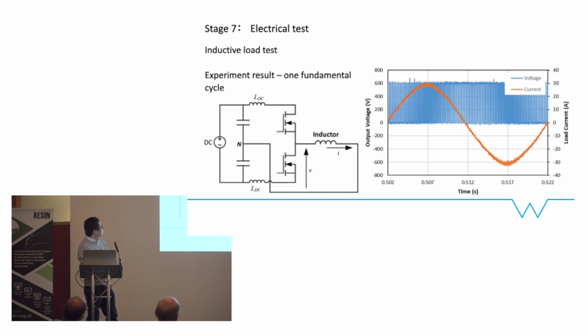All right, lastly, we did this inductive load test, in which we put our power module in constant switching operation. This is the diagram of the test circuit. With this circuit, with limited active power input, we can have large AC current circulating in this loop. This is one of the results at 600 volts DC link, and the current is 30 amps peak. We carried out different tests for switching frequency from 5 kilohertz to 20 kilohertz, and current from 10 amps to 30 amps and up to 70 amps. So all the tests were successful. That proves the power module functions properly.